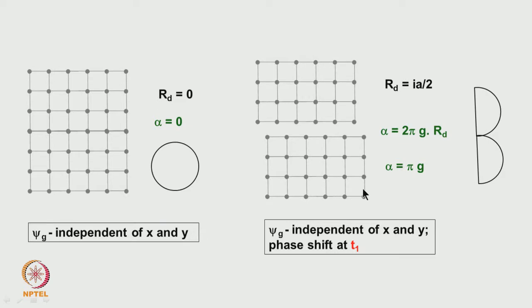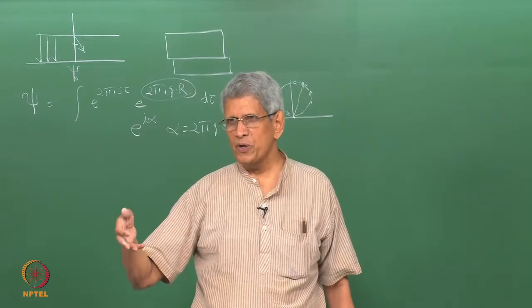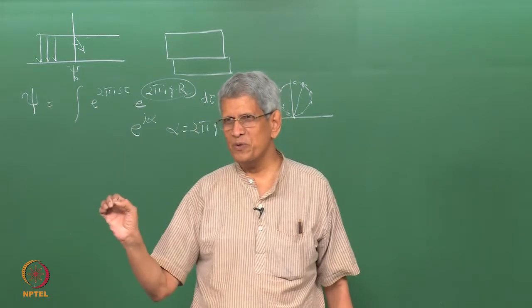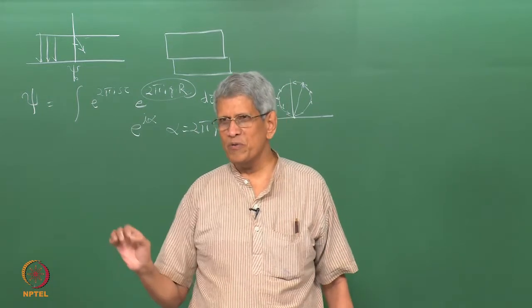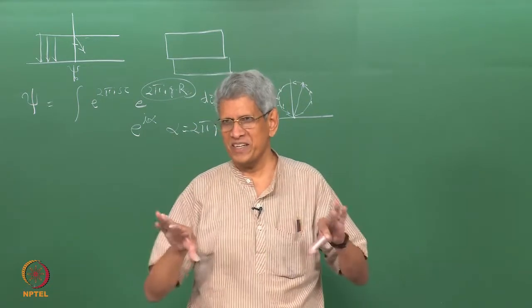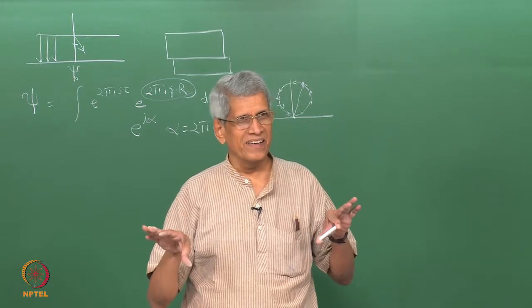That is, in some regions the amplitudes all add together, in some places they subtract and become 0. Then you take the square of it. So as a function of distance, it is going to give rise to a fringe contrast. That is how all planar defects give rise to a fringe contrast. Is it clear? Okay.